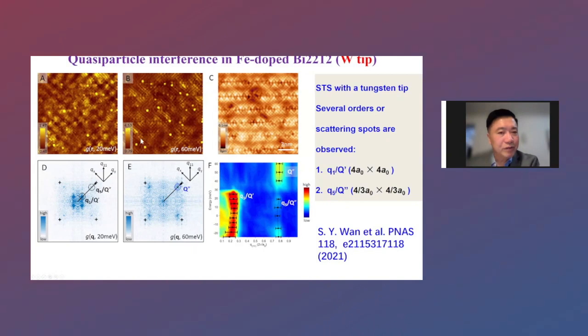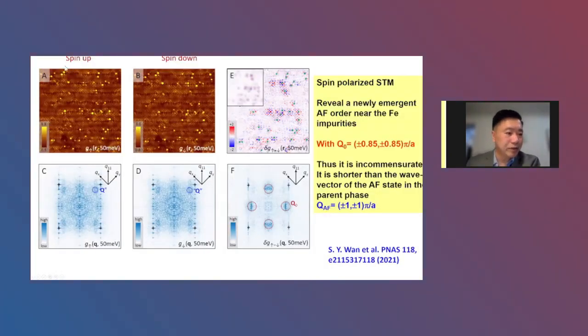However, if we use a spin polarized tip for tunneling spectrum, for spin up and spin down, and then we subtract these two topographies, you will see that nearby this iron impurity, you see clearly this antiferromagnetic order. The blue and the red show antiferromagnetic order. This is the Fourier transform. After subtraction, you can clearly see these spots, which correspond to this antiferromagnetic order, but it's an incommensurate static antiferromagnetic order. It is a little bit less than the Q vector of the antiferromagnetic order in the parent phase, okay, which is about 0.85. For the parent phase, the antiferromagnetic order is 1 here, okay?